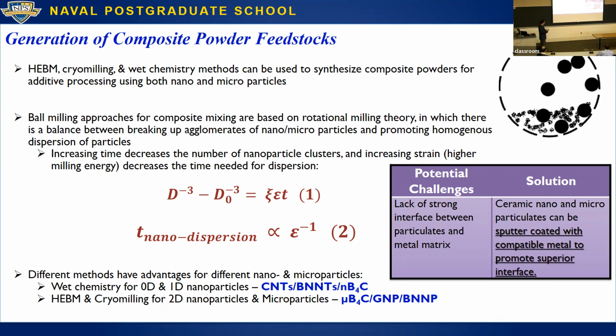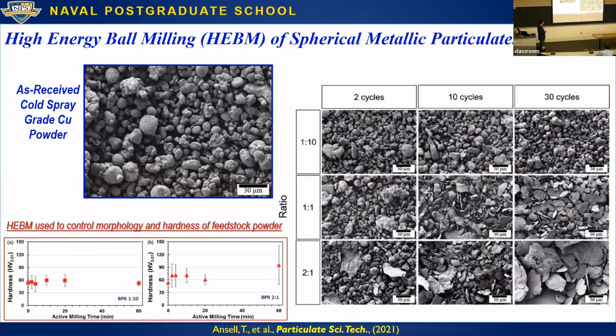Depending on the technique, we can use nanotubes, nanoplatelets, and zero-dimensional particles. We've also done a lot of work focusing on metallic powders for AM in general, because before we even add the reinforcement, we need to make sure that the metallic powder is going to have good properties. Most of what I'm going to talk about today is 3D printing, which has some of the most sensitive requirements for the powder.